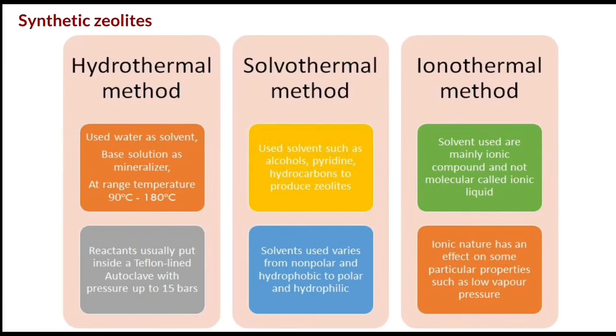The reactants to synthesize zeolites are mainly silica and alumina. The reactants are usually put inside a Teflon-lined autoclave with pressure up to 15 bars for optimum zeolite production.